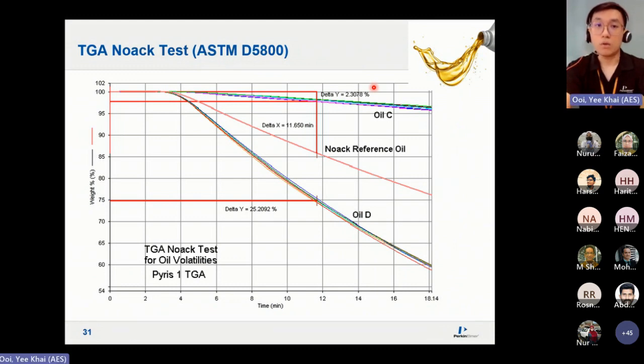Then this is for lube oil. This is also another standard method that lube oil manufacturers need to comply with. So you have a reference oil you need to match it with. We sample at a reference time, usually at 11.65 minutes, and monitor the weight loss. So you have two oils. Your oil cannot be too volatile, because as you run your engine, it's going to evaporate and then cause damage to the engine.